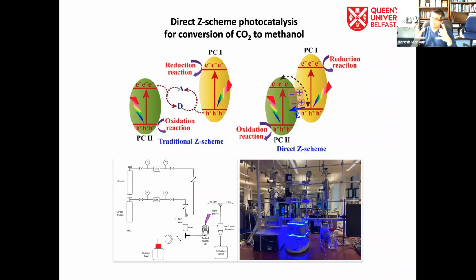or using graphene, carbon-based materials, which is a more complicated type of catalytic system. The more advanced system is the direct Z-scheme. Instead of the traditional Z-scheme, we are using direct Z-scheme photocatalysis here. So here you have a combination of two metal oxides, a photooxidation catalyst and a photoreduction catalyst. In this case, we are using zinc oxide and manganese oxide, which is a friend of ours, and we have been using them for several years in our lab. As I said, this is not just about the catalyst, this is also about the reactor. We have designed a new reactor, which is both batch as well as continuous flow type, for this type of reactions.